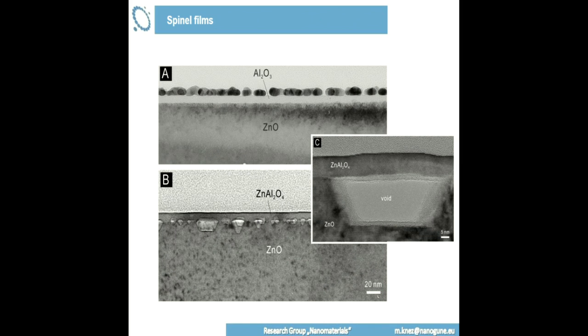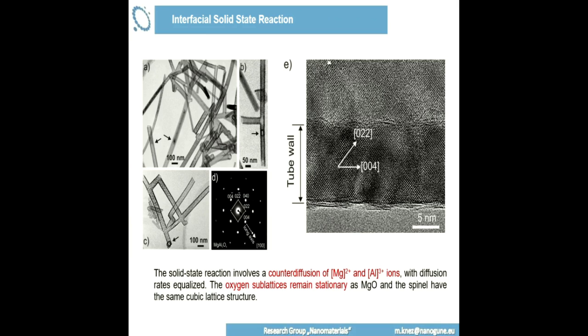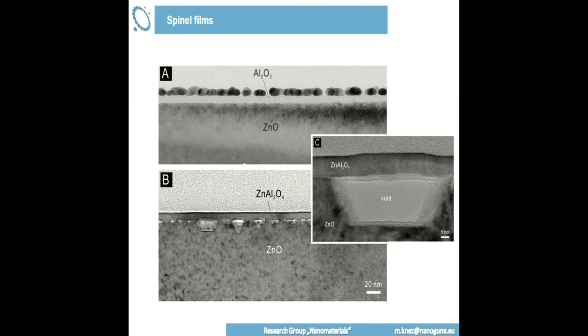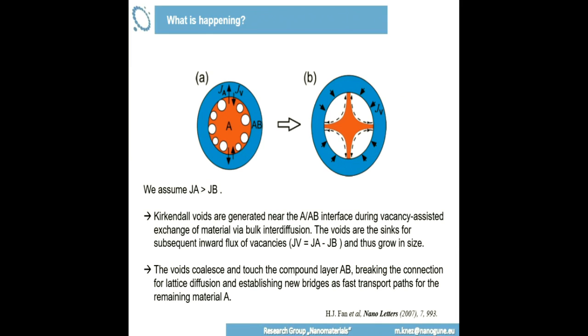And this is just because of your thermal treatment, which then generates those voids at the interface between two materials. In this case, you don't have the same lattice, or not even a similar lattice, and therefore the rearrangement of the crystalline structure is triggering this void generation. Because you don't have, for example, oxygen as a stationary system, which is the case in the previous case. If the lattices are different, the oxygen is not stationary, so it's going to migrate as well, and then it's going to generate the voids. So interfacial diffusion is an issue in many of the materials, and you need to be aware of them as well.